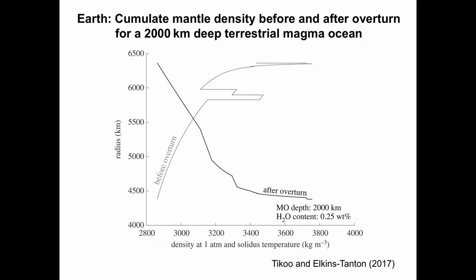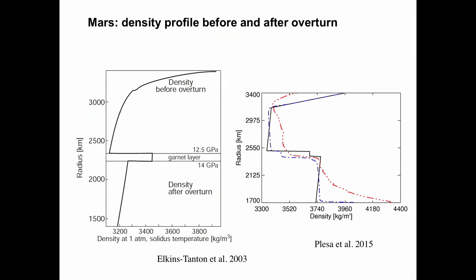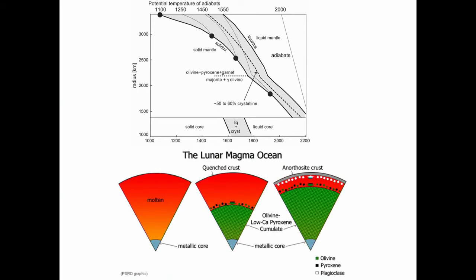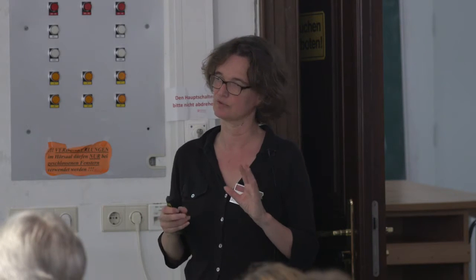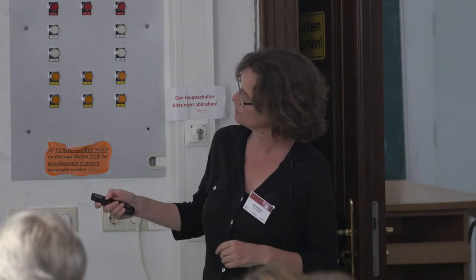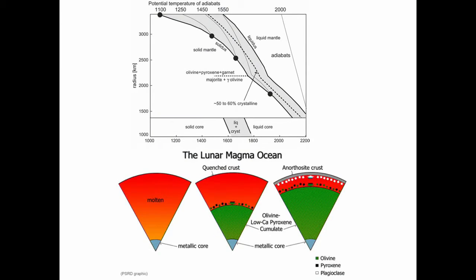Here's a case for Mars, where it's similar, where at the surface we would produce an iron-rich crust. More interesting is probably the moon, just for completeness. You see that in the case of the moon, because it's smaller and because of the composition of the magma ocean, it's interesting because first you produce dense crystals that sink down. When you crystallize the magma ocean by approximately 80%, the crystals you produce at that time are plagioclase, which rises up because it's lighter. So on the moon, what we see today is this anorthositic crust consisting of plagioclase at the surface, and the magma ocean crystallizes then from the bottom in between.